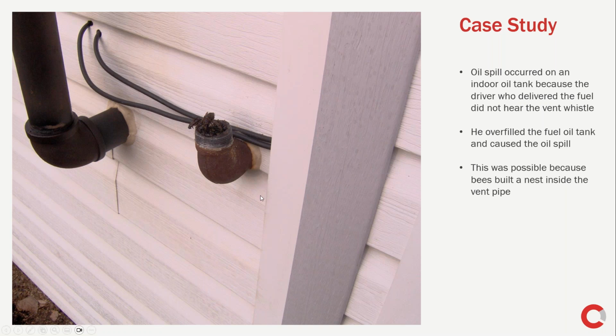The oil spill occurred because the delivery driver didn't hear the vent whistle, which is an indicator of when the tank is full. Vent whistles are installed on vent pipes of fuel oil tanks, and they are designed to produce a whistling sound as air escapes from the tank during the filling process. So when the tank is nearly full, the rising oil level blocks the vent pipe, and this causes the whistling sound to stop, which serves as an audible signal to the delivery person that the tank is full and you should stop adding fuel to prevent overfilling.